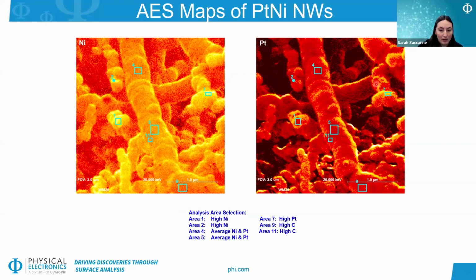In the platinum map, this area appears slightly brighter, and in fact, that is a more high platinum containing area as well. These other areas on this larger wire in the center have more of an average blend of nickel and platinum detected in those regions. And then there was this one area that had specifically higher carbon amounts as well.